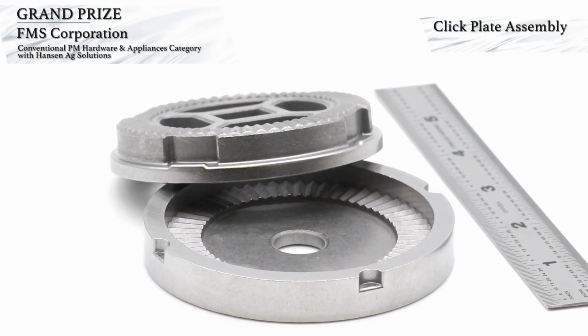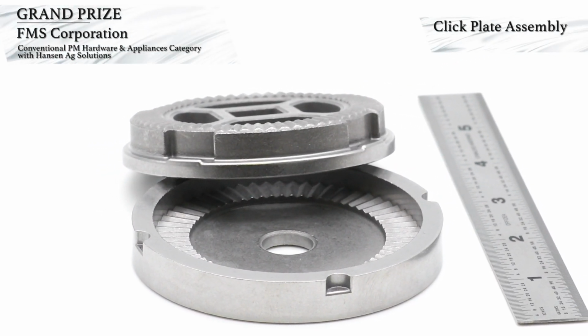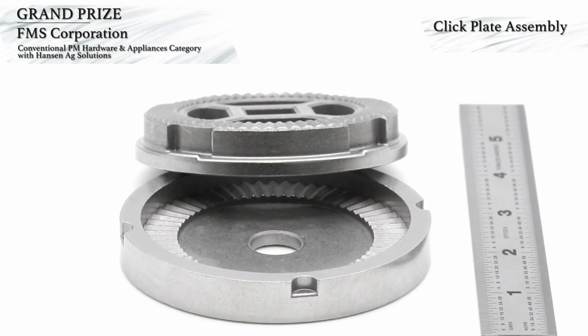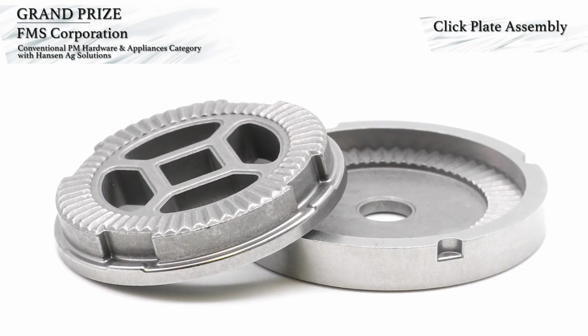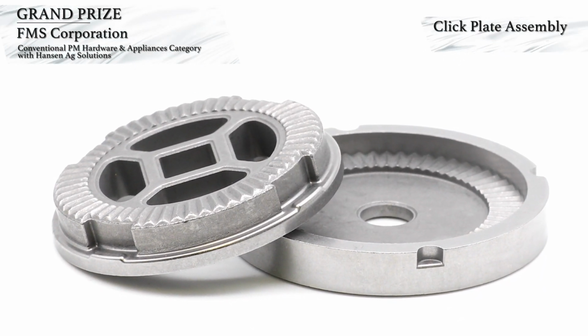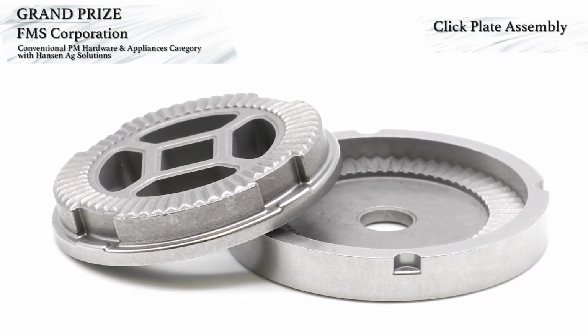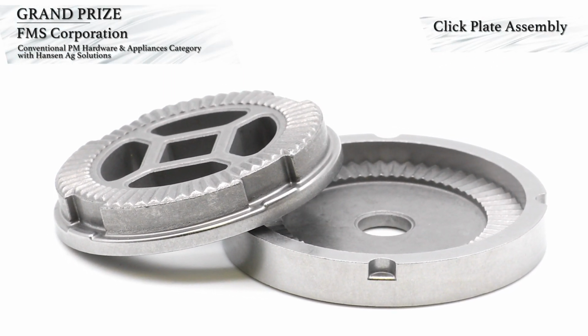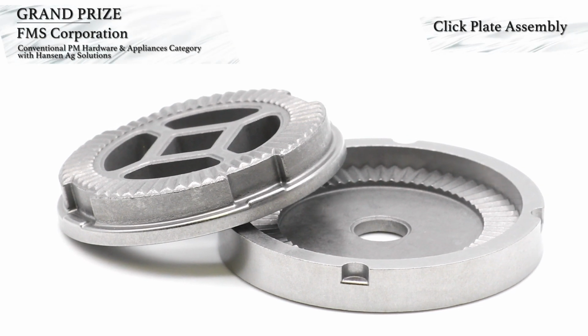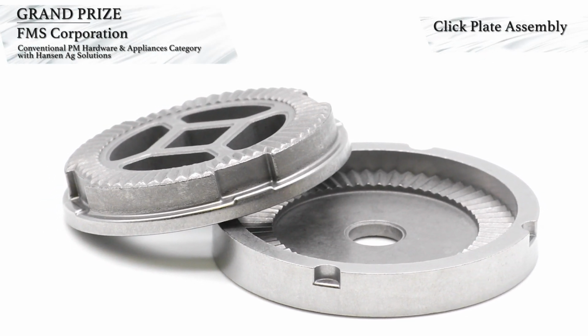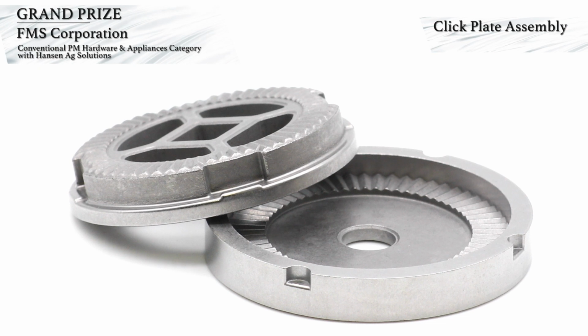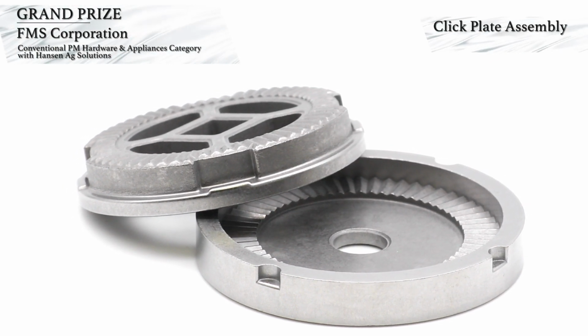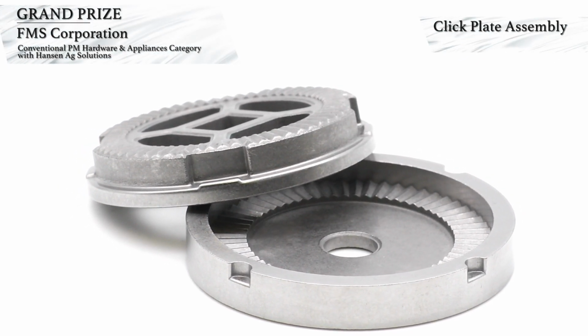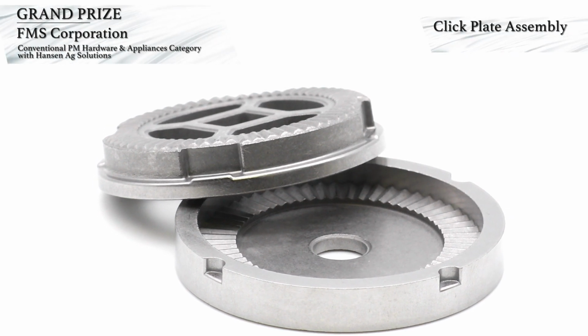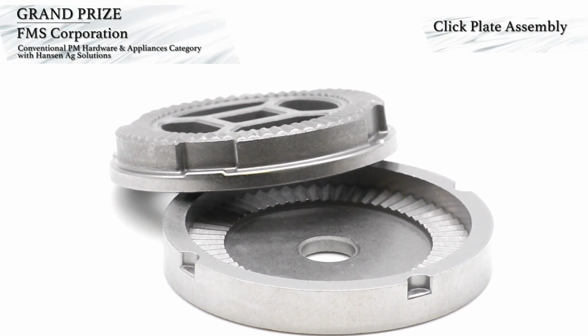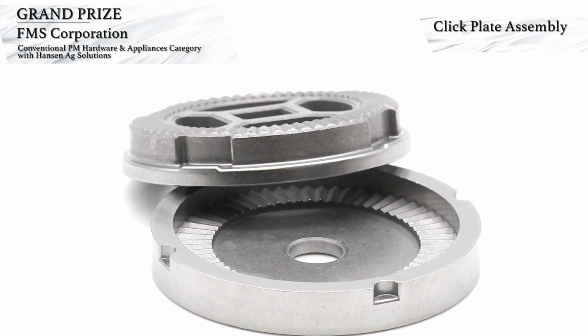A mirror finish is required on several punch faces in both tooling sets in order to form both the customer logo and the interlocking teeth correctly. An accurate taper is needed on the core rod assembly for the inner plate due to the low compressibility and abrasiveness of the SS-410 powder. The PM click plates have been tested beyond 1 million click cycles, approximately 1,500 years of use. The parts are sinter hardened to achieve micro indentation hardness equivalent to 55 HRC.